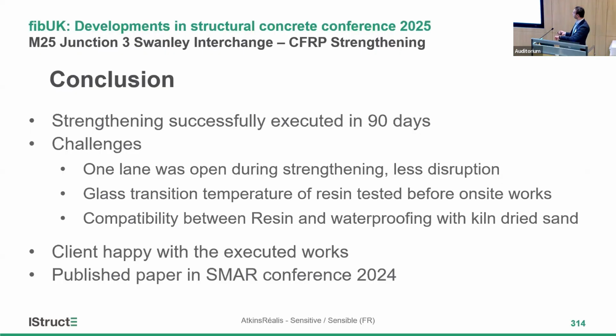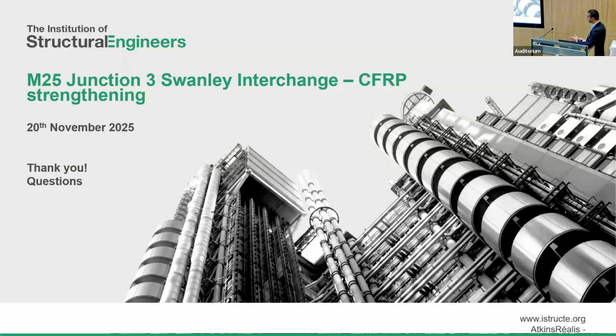So in conclusion, strengthening was successfully executed in 90 days. Challenges we faced? Multiple, but to point out, one lane was open during strengthening, so there was less disruption to public. Glass transition temperature of resin was one of the challenging ones. There was compatibility between the resin and the waterproofing with kiln-dried sand, which improved the adhesion. Our client was happy with the executed works, and we published a paper in SMAR conference in 2024. So with this, I come to the end of my conclusions, and I'm open for questions.